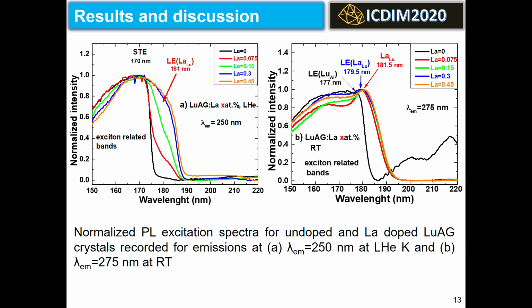Interestingly, with increasing lanthanum content, and thus the content of impurity centers, the excitation bands become broader. This fact might indicate that radiative annihilation of low-energy excitation takes place mainly at the irregular, perturbed sites of the crystal lattice, which means stabilized by lanthanum-lutetium centers.